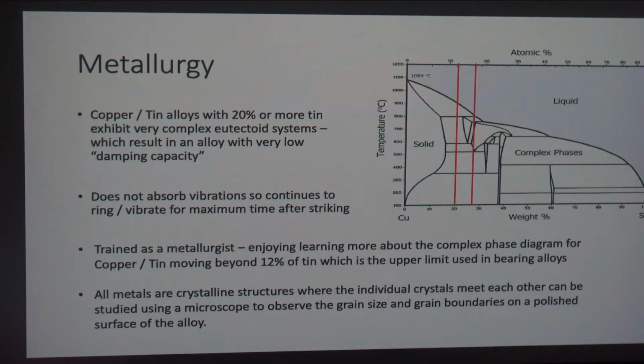And what that means is all those complex eutectoids are freezing out and pushing into each other, and they lock into each other at the grain boundaries. The reason metals are ductile is because the grain boundaries normally are flexible. You can bend a piece of steel and the atoms will hop around the grain boundary. Well, these grain boundaries are locked up because of the way the eutectoids have formed. And the good news about them being locked up is they won't be ductile.